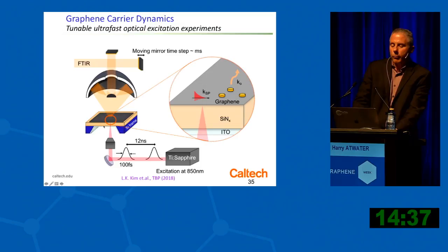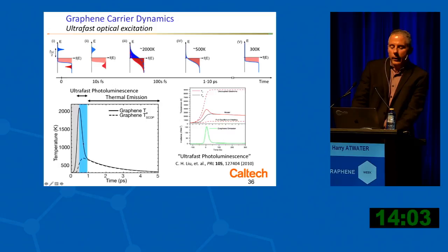And so in an experiment, we looked at the far-field radiation emanating from a graphene sheet. In this case, it's a continuous sheet of graphene where the Fermi level position in the graphene is controlled by a counter gate that's optically transparent, made of indium tin oxide, and light is outcoupled through scattering antennas, which are sparsely distributed on the surface. So we're optically pumping here with ultrafast excitation from a Ti:sapphire source with approximately 100 femtosecond laser pulses. And what we can see is that if we look at the laser fluences applied here, we expect, during the electron-electron relaxation, to see an equilibration of the electron gas out of equilibrium with the lattice. And then during a short period on the sub-picosecond timescale, from a few hundred femtoseconds out to about a picosecond, there's a region where we can see